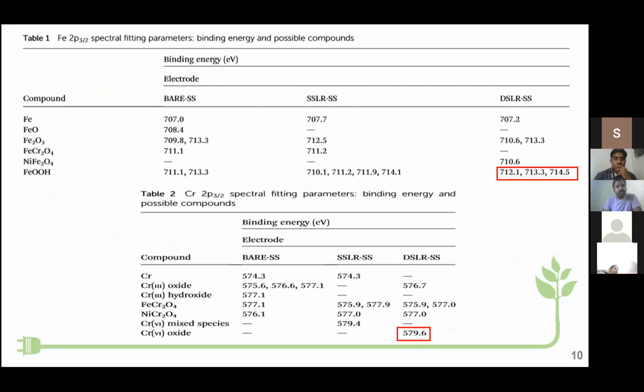Table 1 represents the Fe 2p 3/2 spectral fitting data. Here you can see the differences. The major difference is that, when compared to bare stainless steel, this laser textured stainless steel possesses higher oxidized ions, that is Fe3+, Fe3+ oxyhydroxide. More 3-valent ions are formed over the single as well as double side laser irradiated stainless steel. Likewise, chromium 6 oxide, a higher valent oxide, is formed only on the DSLR, that is the double side laser irradiated stainless steel.